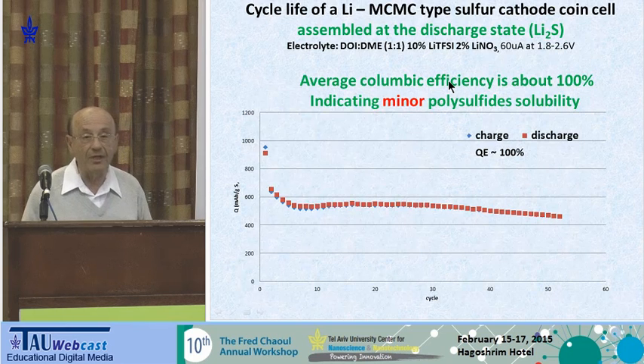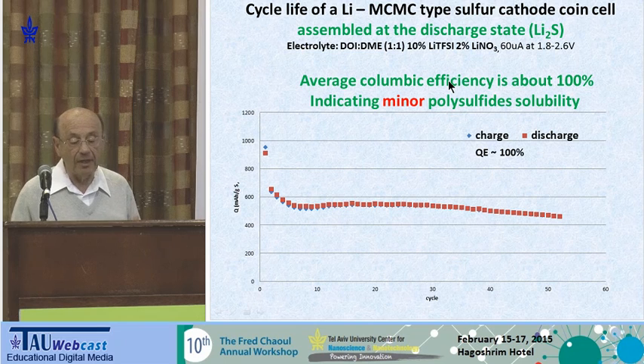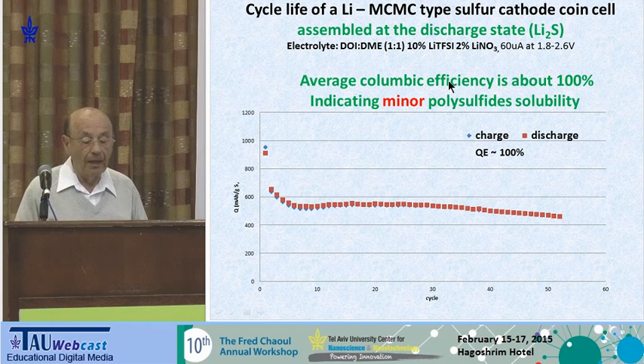So we build from this kind of a cathode, sulfur cathode, that we assemble it in the discharge state when we have lithium sulfide. So first time we charge it and not discharge it, and we got very stable cycle life, and about more than 50 cycles still running. But the major issue here is that we have close to 100% Coulombic efficiency. That we mean if we charge it by 100 capacity unit, we get back 100, and not like in the case of solubility of polysulfide that attacks the lithium, it's between 90% to 98%. So this is quite good evidence that our concept is right, and polysulfide are not coming out from the cages.